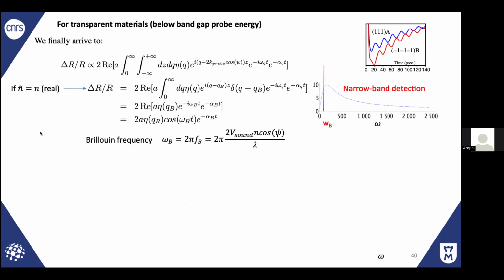But take care about something. If the refractive index is real, it means you probe below the band gap. You look at a transparent material. In that case, the wave vector of the light is purely real, and that integral is simplified to the Dirac function. In that case, you come back to what we call the Brillouin oscillation, and you detect only one oscillation typically like that. In that situation, we excite gallium arsenide, and we see only one single frequency.